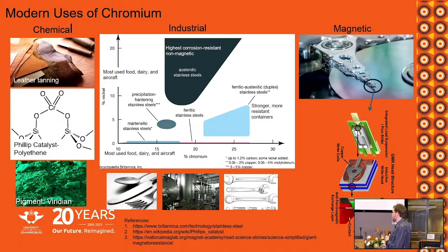I see some of my students are here, they'll recognize the nice green color. If you make a mistake in the arc furnace, that's what you get as a result, and that's the end of a sample. Typically you only find out 3 days down the line when this happens. Then you throw the sample away and you start all over again.